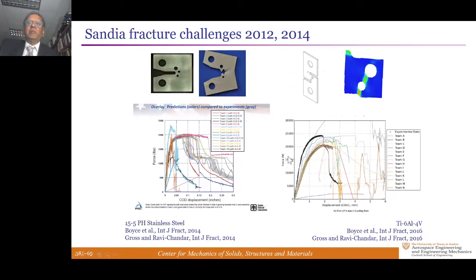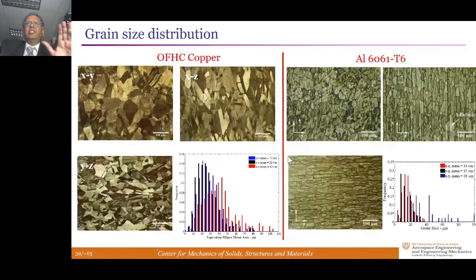I started looking at this about 10 or 12 years ago, and we had this idea we need to look locally at the picture of what happens to plastic deformation and failure mechanisms in a variety of materials, both pure metals and metals or alloys that have impurities of various kinds. So we chose an oxygen-free, high conductivity copper, 99.99% pure. No alloying elements, no second phase particles, nothing. And the grain structure is shown here. They are kind of platelet-like grains that are oriented in the direction of rolling.